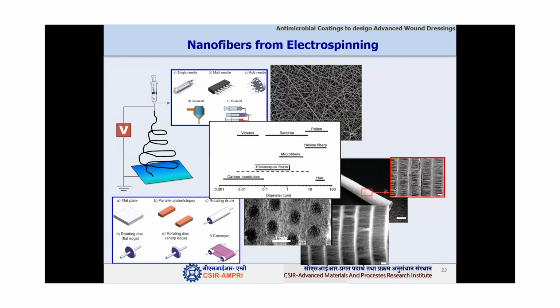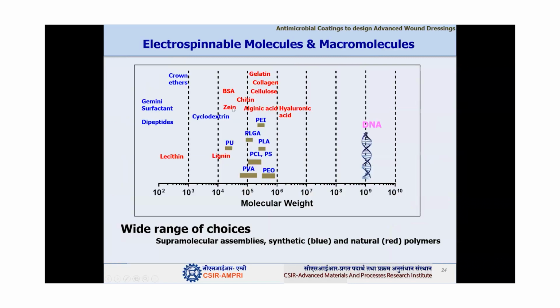So you can see here that from a few nanometers to 100 micrometers size, nanofibers you can design using this electrospinning technique. And there is a wide variety of choices of materials which you can spin in the form of nanofibers, starting from the dipeptides, crown ethers, supramolecular assemblies, then your natural polymers like gelatin, collagen, chitosan, or synthetic polymers like PCL, PVA. Any kind, including the DNA. So you can easily get reports where people have electrospun DNA nanofibers. So it is a very versatile technique.